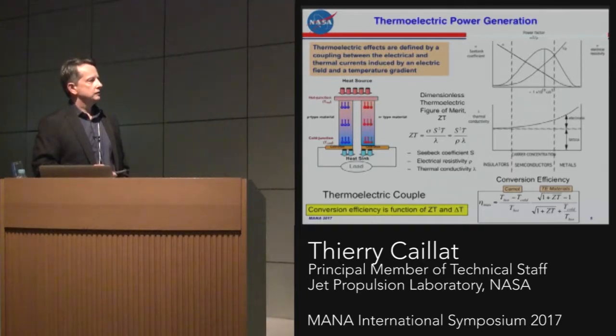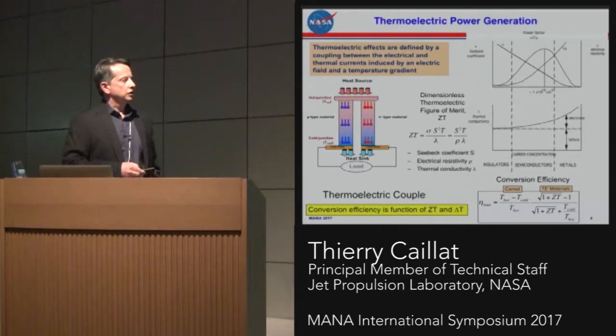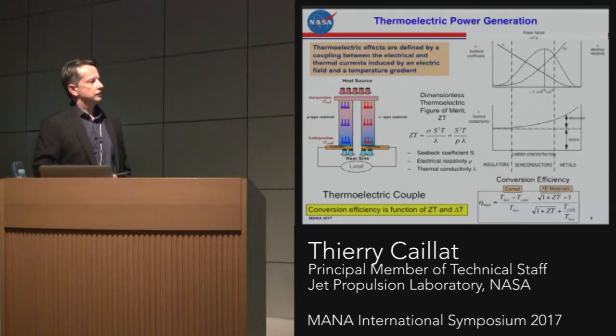We define a dimensionless thermoelectric figure of merit by multiplying by the temperature, and ZT is the dimensionless thermoelectric figure of merit. Typically, all of these are coupled, so unfortunately you cannot optimize all of them at the same time. You need to compromise, and that's the cartoon here, which shows across the spectrum of insulators, semiconductors, and metals what the best compromise is between those three properties. Typically we are dealing with heavily doped semiconductors. That's where the best combination of those three properties occurs, and that's where you get optimal ZT.